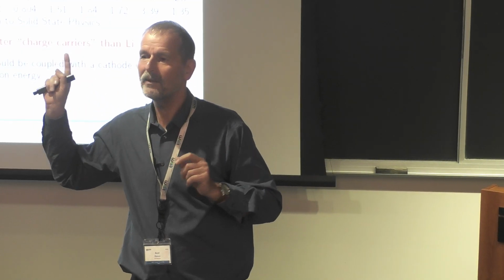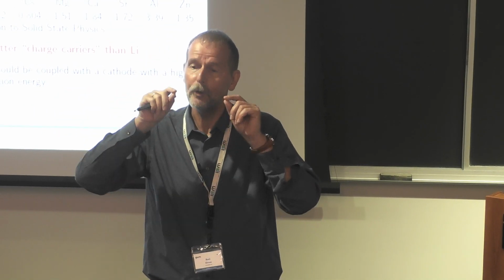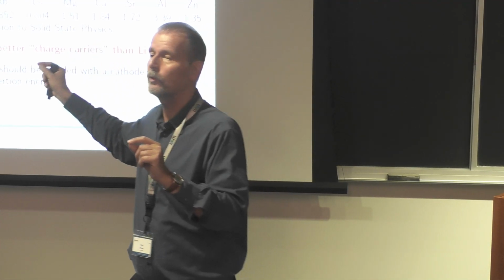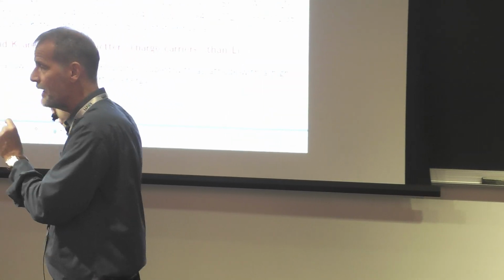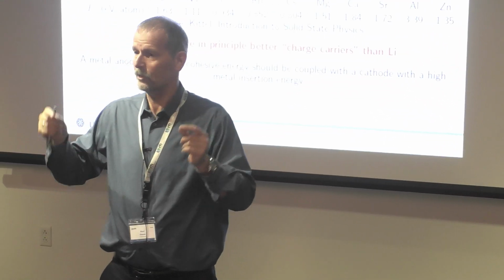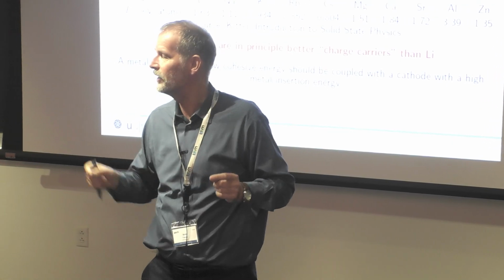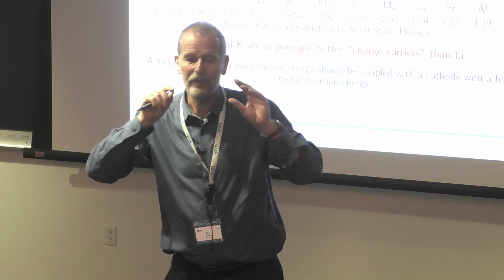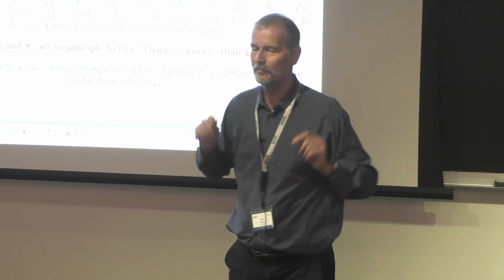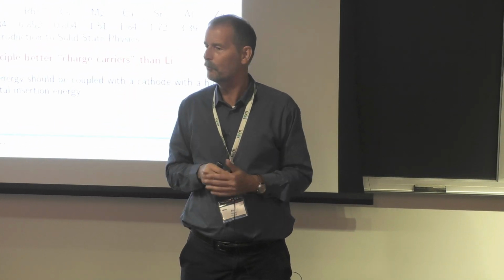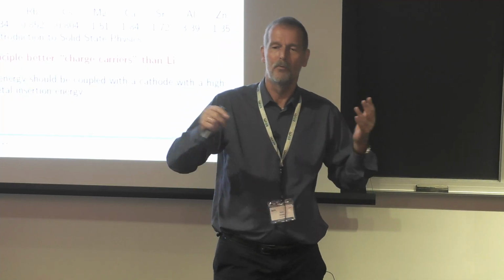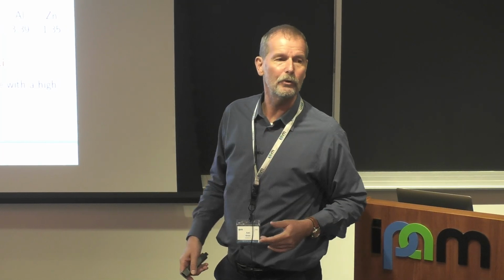And also, for the metal anode, there is no better metal and no better anode than the metals. Because of course you want to have a low binding, but if you have an anode that binds lithium, for example, less strongly than the cohesive energy, then it would never get in. Then you have this plating. We have already the best. So when we hear things of saying, yeah, we increase the capacity of the battery 10 times, it's nonsense. There are physical laws prohibiting it. Of course, there's still room, and a lot of room, but it's different from semiconductor physics. There is no room at the bottom anymore.